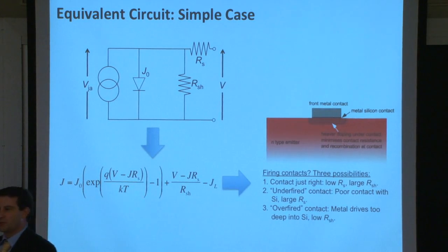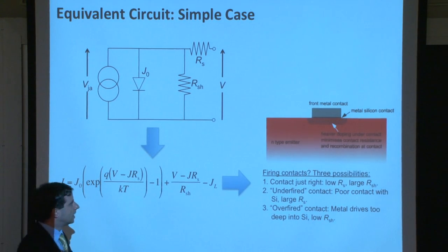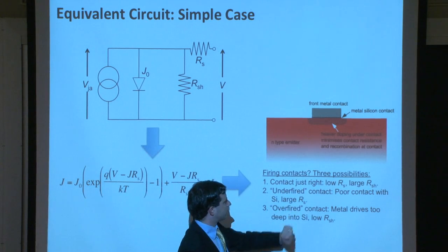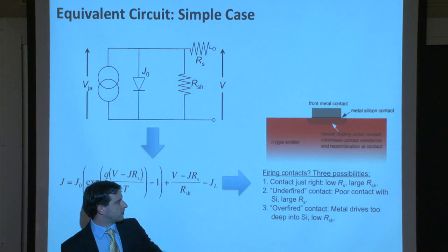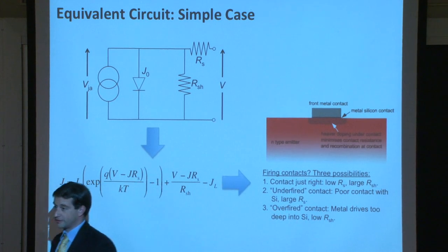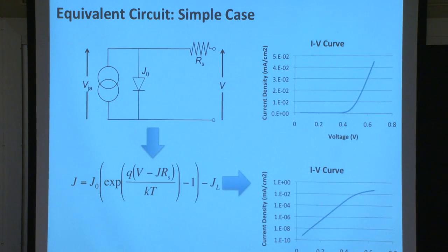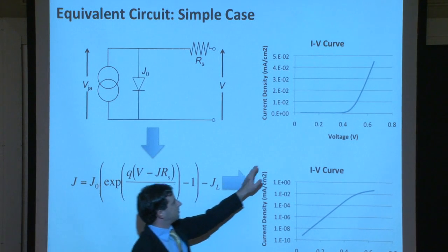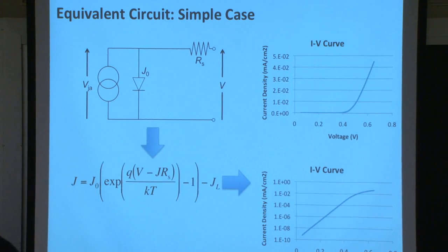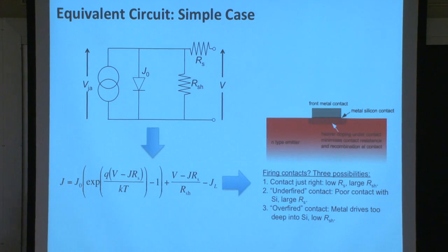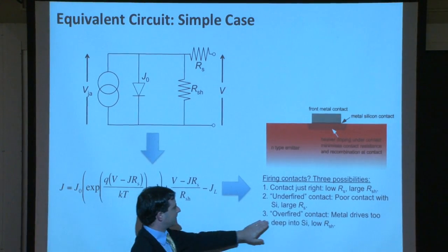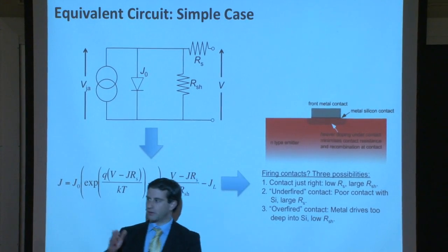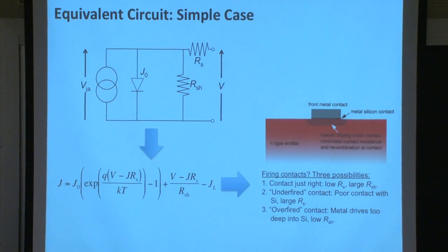If you don't get the chemistry just right at the interface, maybe you didn't clean your sample properly, maybe you didn't heat it up high enough so that the atoms really started to interdiffuse and interact, you can underfire your contact, and that results in poor contact with your semiconductor and large series resistance. So large series resistance will essentially impede charge flow and result in a fill factor loss. On the other hand, if you overfire your contact, let's say you heat it up but fire it a little too long, then the metal or the contact material can drive too far into your semiconductor and wind up shunting your device.